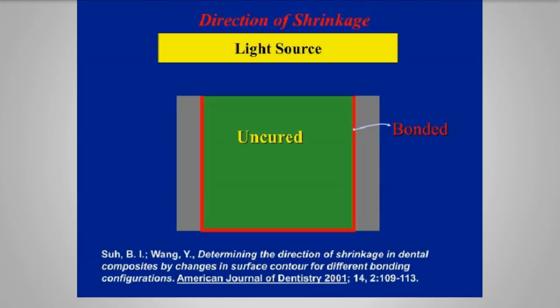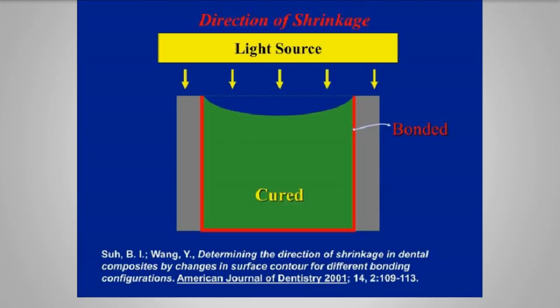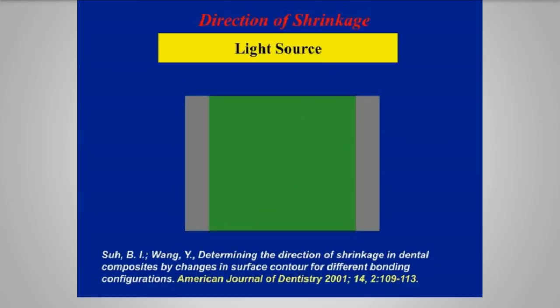So one of the pitfalls, again, thank you, Dr. Sa and Bisco, for giving us this information, is that when you have a substrate of material, could be conventional light cured material, and you have your bonding adhesive in, and you have your light source. When you polymerize the material, you're going to get some volumetric shrinkage, maybe 57 microns. This is in the literature. This is what happens. Now, if you do the same schematic again, you have your bonded interface again. Doesn't make any difference which adhesion it is.